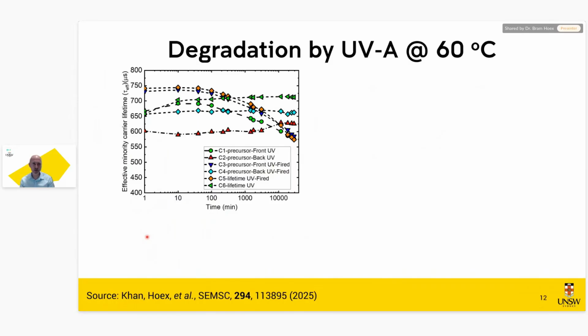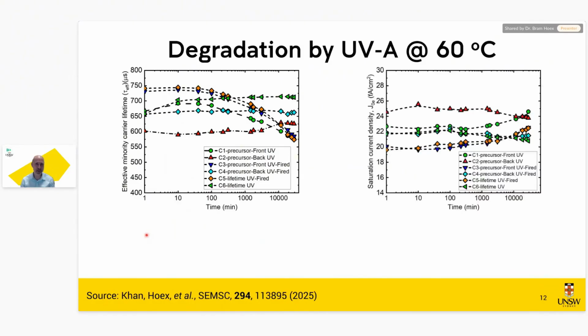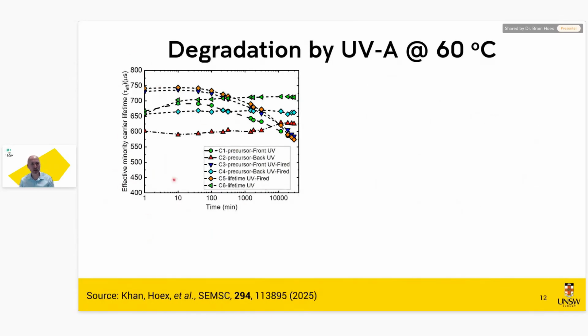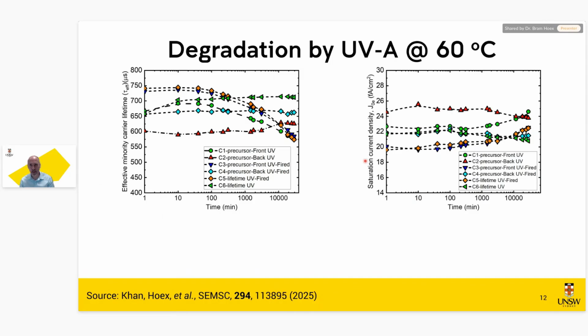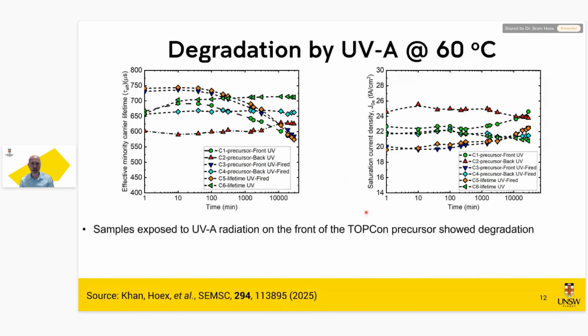So we were checking if we use the same intensity, if they would show the same degradation. So this was the result with UVA. So it's still harsh UV. I would not be happy being in that climate chamber myself. And what we saw is that in this case, we looked at the effective lifetime of lifetime samples, and we saw a reduction of the effective lifetime. So we saw UV damage, and this UV damage we could mostly attribute to an increase in the saturation current density, in this case, at the surface. So we saw significant damage due to UVA. But the interesting thing is that we only saw this damage at the front. The rear, we did not see anything.